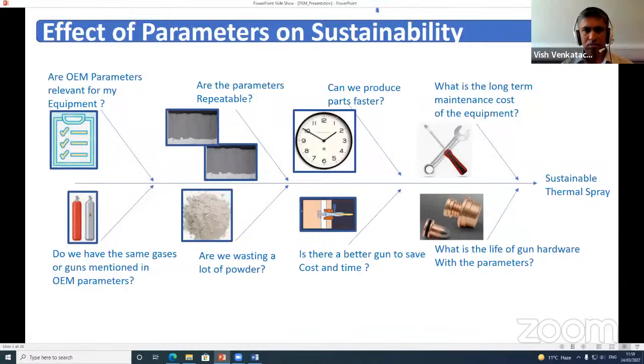Do we have the gases that the OEM is suggesting? And if I take that OEM parameter and spray multiple times, am I going to get a repeatable microstructure? Am I using the right gun to not waste a lot of powder? Am I putting a lot of powder on the floor? Can I improve the deposition efficiency? Can I spray faster for the same thickness? Can I spray faster and get the parts out? Is there a better gun to save cost and time? Can I use a larger bore plasma spray instead of a narrow bore?